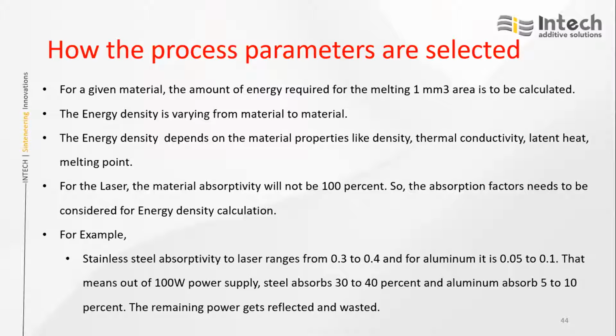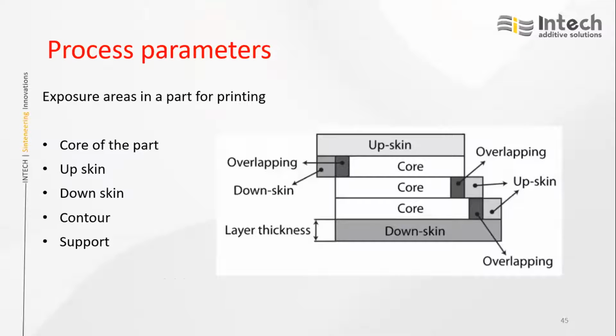For aluminum, it is only 5 to 10%, meaning 90% of the input power gets wasted. So the laser absorption factors for a given material we need to take into account. In that ratio, we need to multiply the required energy density, and finally we have to optimize the process parameters.